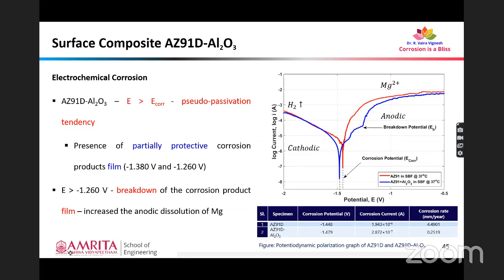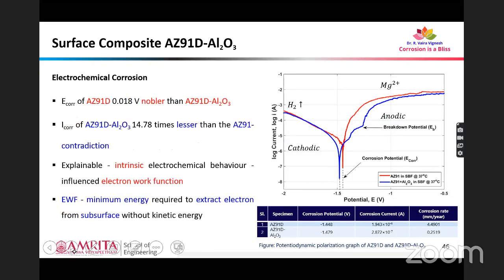And coming towards the corrosion current and corrosion rate of the specimens, from the electrochemical analysis, the base material's corrosion rate was around 4.49 mm per year, and that of the composite was around 0.25 mm per year. So from this, we can conclude that the corrosion rate determined from immersion is the same, and it is equal to that of the electrochemical corrosion analysis. Yes, and coming towards the corrosion rate of the materials, the corrosion potential of the base material was 0.018 volt more noble than that of the surface composite. However, the corrosion rate of the composite is 14.78 times lesser than that of the base material. So that is a complete contradiction.